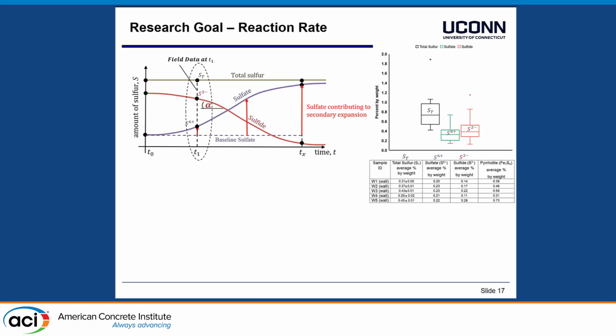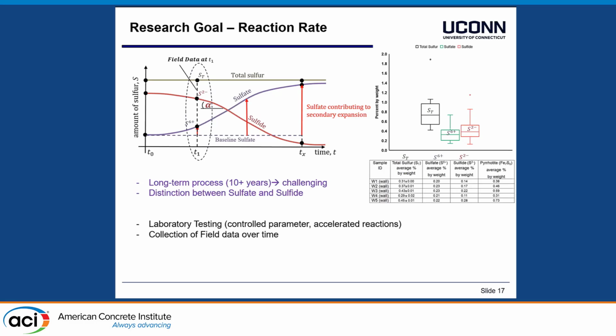What does this mean? We cannot say, because this is research still going on, but we can only say to the homeowners that in comparison to other tests which have been performed at the moment, you are in the lower 10 percentile or lower 50 percentile or higher 90 percentile. So we can place them so that they have at least an idea where they are in comparison to others.